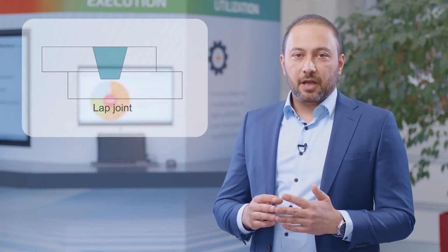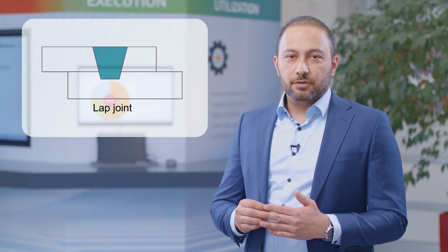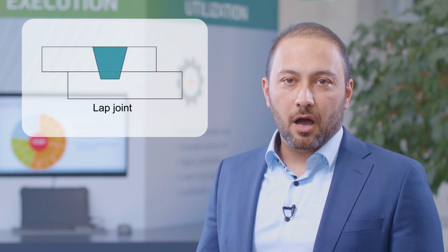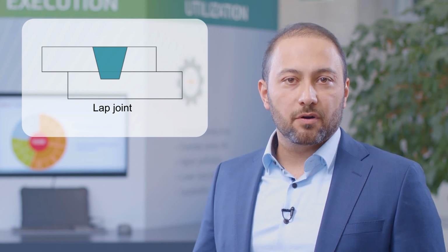For overlap joints, the situation is different. Here, the gaps are horizontal and can usually be pressed down to a technical zero gap with the use of a clamping device. However, problems arise when discontinuities are present in the overlap area. Examples are hot cracks in cast components or excessive pores and blowholes. The height offset in this case would be about 0.4 mm, which equals 0.02 inches. Differences exceeding this must be mechanically machined. This can, for example, be done by grinding or milling.